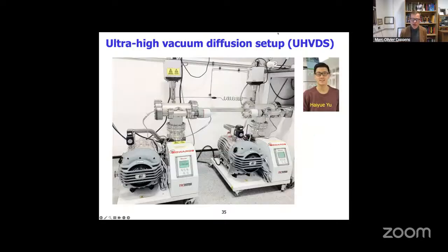And so in my lab, we built this equipment with an ultra-high vacuum diffusion setup. This is inspired actually by the original experiments of Knudsen himself in 1909, and really the pioneers in this field, who were clearly interested in vacuum equipment. This was also the birth of quantum physics, which propagated these interests in these studies. And if you are at very low pressure, clearly the diffusion of gases is dominated by collisions with the wall, right? The mean free path can be meters long, right? And so we constructed this out of 2 vacuum pumps with a pipe in between, and we can control independently with turbomolecular pumps the different pressures in this and control the flow through this.